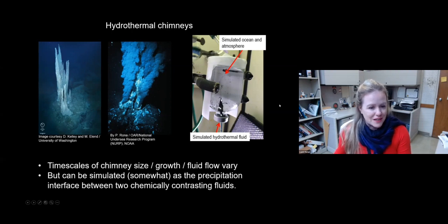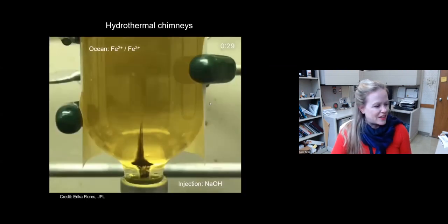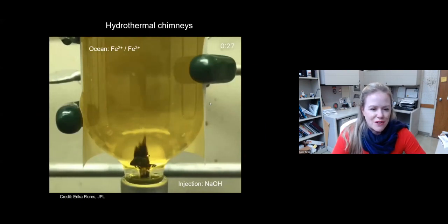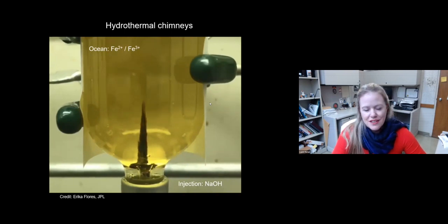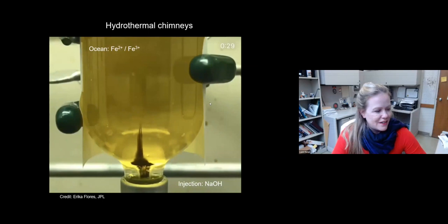And so it's similar in mechanism to what you're seeing at, say, black smoker vents with different temperatures, obviously. And this allows us to test, you know, what structure might form here, how porous it might be, and what sorts of minerals we might make. So what this actually looks like, here's another video of one of our experiments done by my student Erica Flores. And this is a different chemistry. So here we have an ocean that contains ferrous and ferric iron. That's why it looks yellow. And then the injection is not sulfide, but here it is hydroxide.